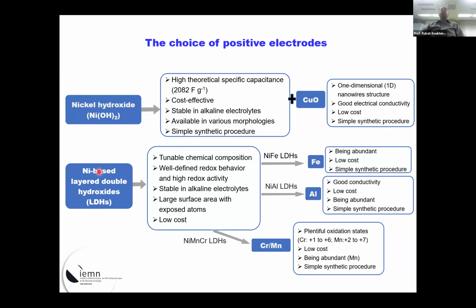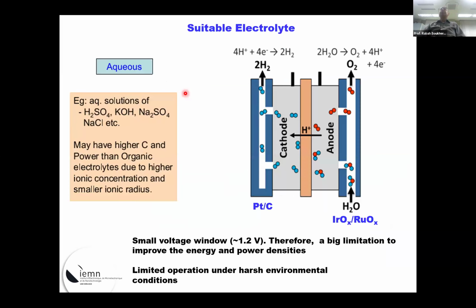So that's why you found a lot of, and also high theoretical specific capacitance. And you can see it here for nickel hydroxide, which is 2082 farad per gram. Now we're talking just about electrolytes. And certainly you do know, if you work with water, what you're facing is the generation or water splitting. It's to generate hydrogen and oxygen, and thermodynamically, it only requires 1.23 volt exactly. So it means when you use aqueous-based electrolytes, you are limited by the operating voltage to about 1.2.